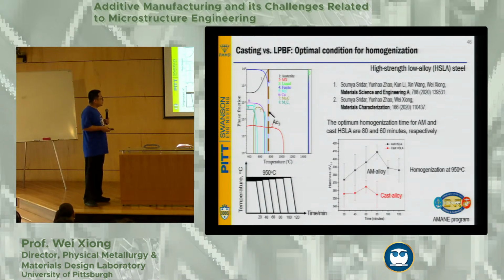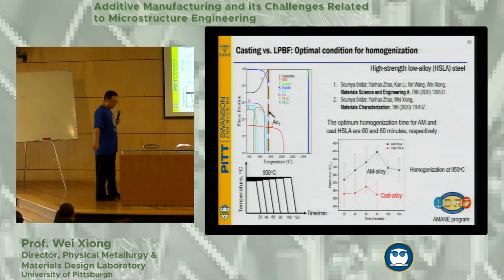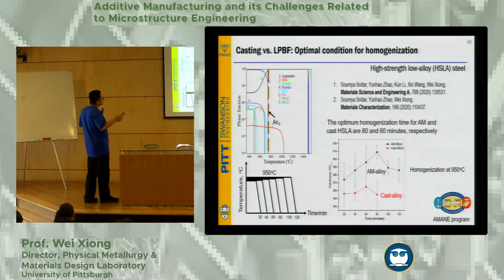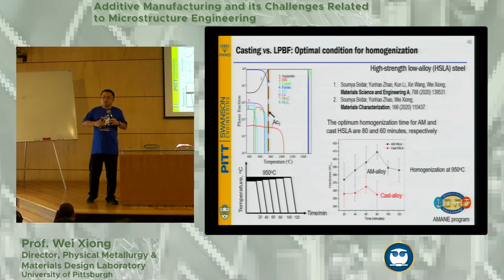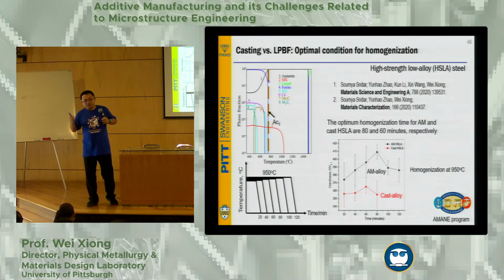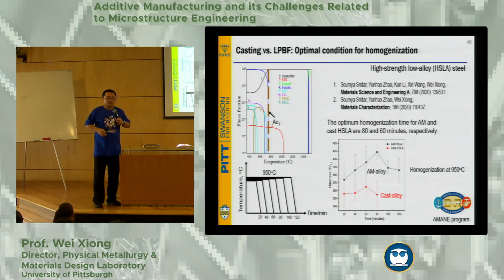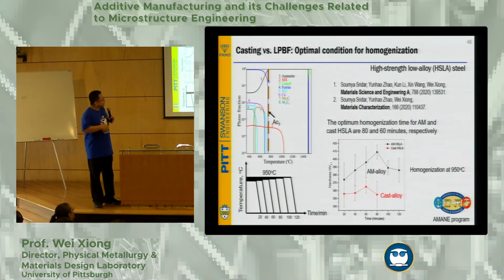For example, yesterday I also talked about high throughput uncertainty quantification using machine learning to customize the high strength low alloy steel composition. I also mentioned the successful tensile test and Charpy test with toughness. Behind that, we also did a lot of work with the post-heat treatment design.